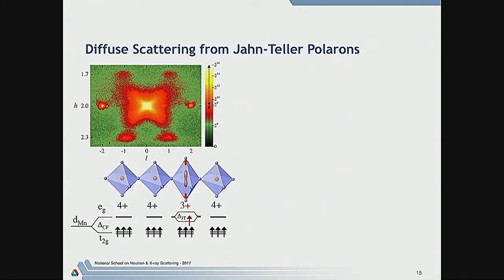So in these cases, you have, for instance, these MnO6 octahedra. Some of them are 4+, which means that the electronic state is spherical. But some of them are 3+, in which case you have what's called a Jahn-Teller active orbital, where, say, an eg orbital is occupied. And that has a tendency to push out the oxygens on either side.